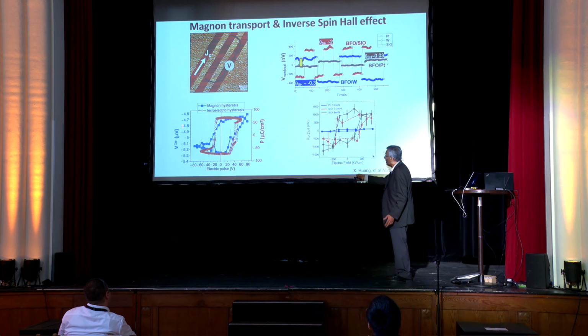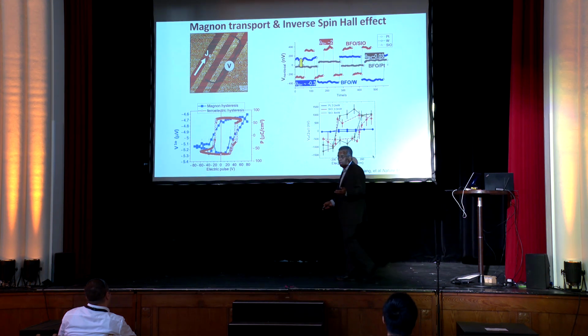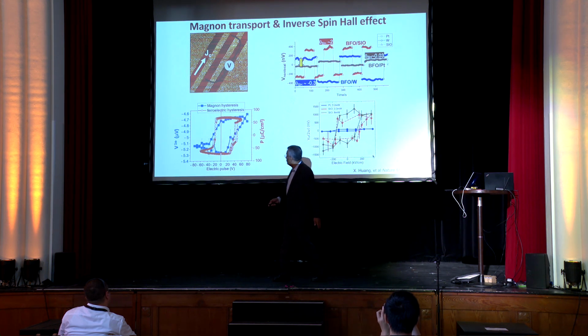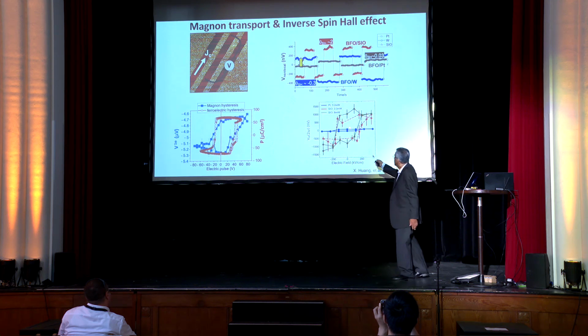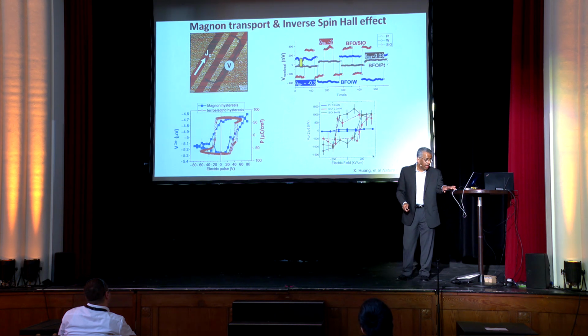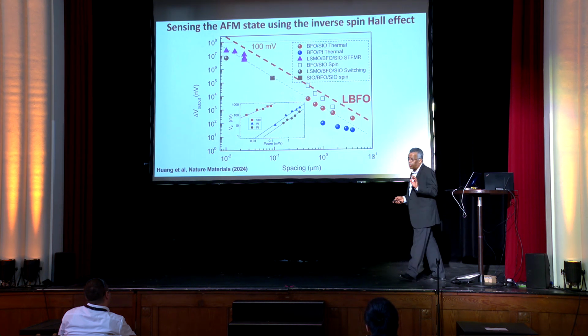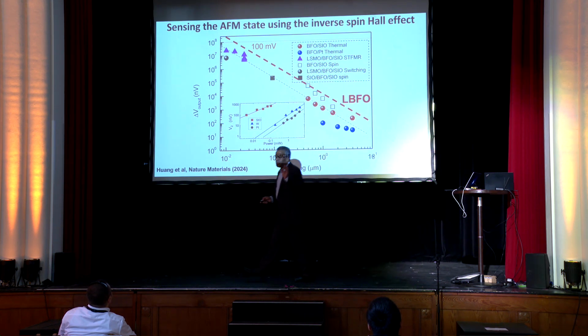We can switch that with an electric field. The red data is the ferroelectricity, and the blue data is the corresponding spin Hall switching. So you can switch it back and forth, and as you can see, it's significantly larger than platinum. And this data is what is exciting, but it's also very rudimentary, very early stage. You have to take it with that spirit.